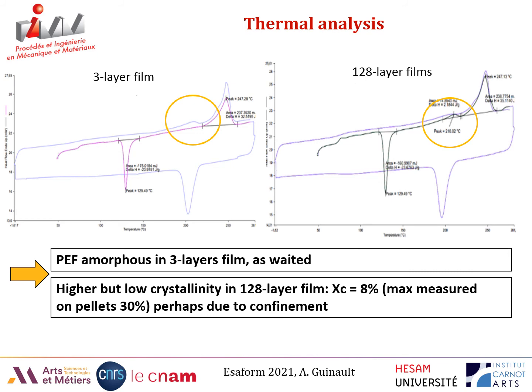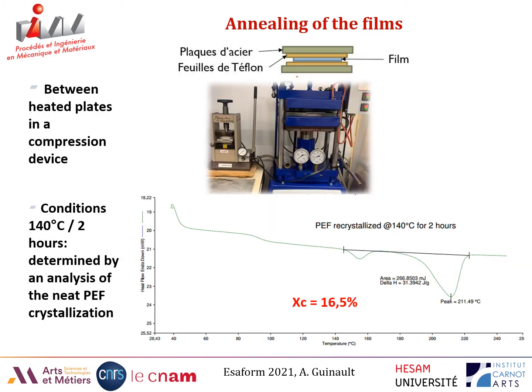So it means that you can calculate a crystallinity degree of around 8%. That is low compared to the one of pellets, that was 30%, but was higher than the one of the 3-layer film, so perhaps due to a confinement effect. So as the crystallinity degrees are not very high, an annealing step was done for improving crystallinity.